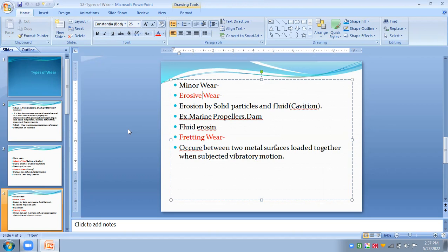Solid particle erosion takes place when discrete solid particles strike the surfaces, and in this erosion process, forces of different origin may act on a particle in contact with the solid surface. In this case, wear rate always depends upon the class of materials and environmental parameters such as impact velocity, impact angle, particle size, particle type, etc.